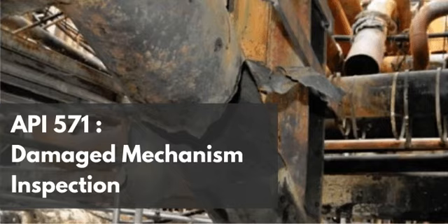Oh, wow. So when the alkaline carbonate fluid breaks down the surface film, it doesn't just find localized tension near the weld. It finds sufficient mechanical driving force 3, 4, or even 5 inches away along the extrados or intrados of the elbow. So the stored mechanical energy just physically pulls the grain boundaries apart as the anodic dissolution eats away the bonds. You've got it.